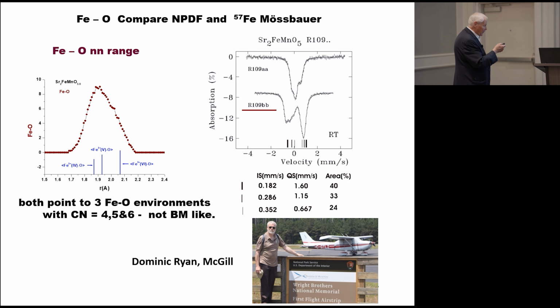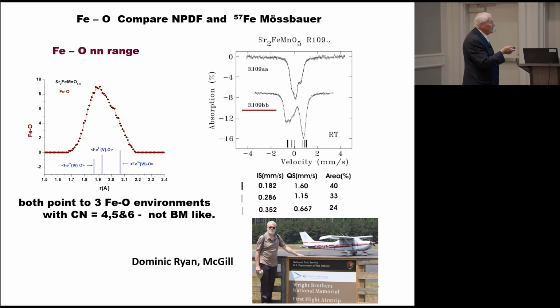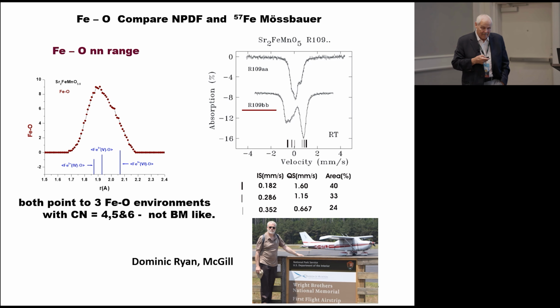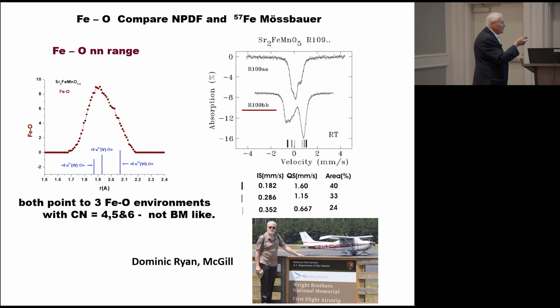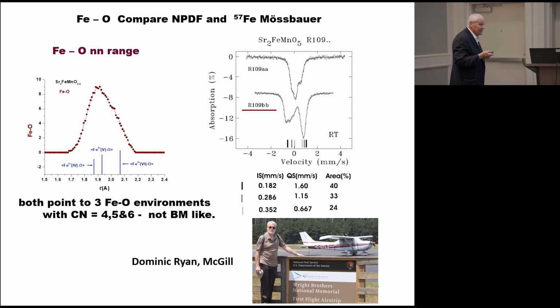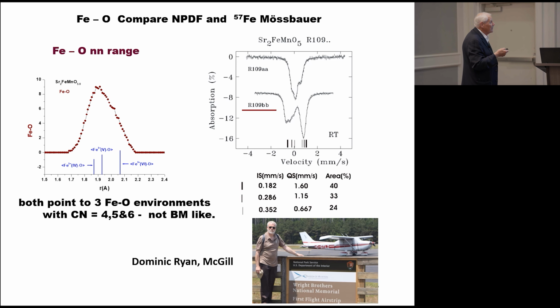This is the partial. You get this rather large blob, which could be consistent with any coordination number from 4 to 6. So that's certainly not Brownmillerite-like, and we went to our colleague Dominic Ryan. That's Dominic in his plane; he actually owns a plane. And sure enough, you can analyze the Mössbauer, 57Fe Mössbauer spectrum in terms of 3 sites. So it's a very complicated environment for iron. So the local structure is down below.